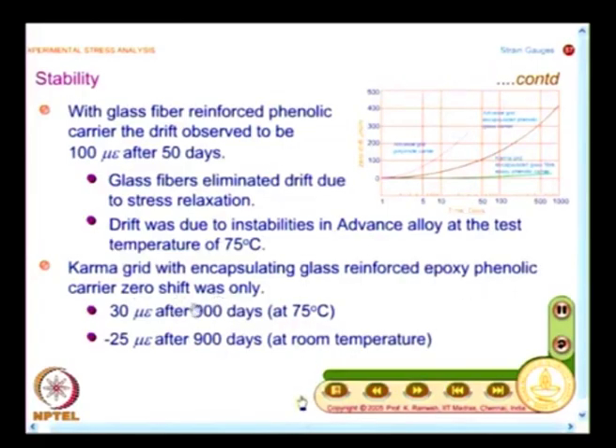Zero shift was only 30 microstrain after 900 days. That means it is almost 2.5 years, and for 2.5 years there is absolutely no problem in your strain measurement. But when I take Karma grid, what happens? It is difficult to solder the tabs. So, you need to go for the factory